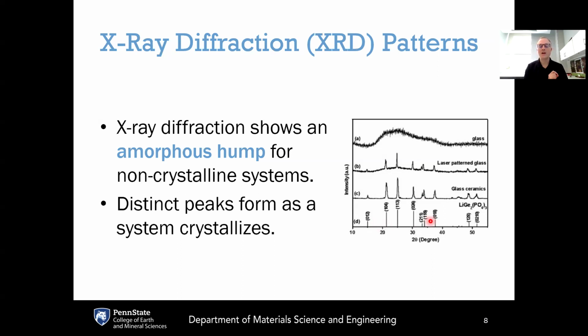So if you're measuring the X-ray diffraction pattern of a perfect crystal, it would give you a set of peaks as shown on the bottom, and then you can use an X-ray crystallography database to look up what is the structure of that crystal and match your X-ray diffraction pattern to the known structure of that crystal. And there's very good software for doing that now, so it's very easy to identify what the crystal is in a material using X-ray diffraction together with those known databases.